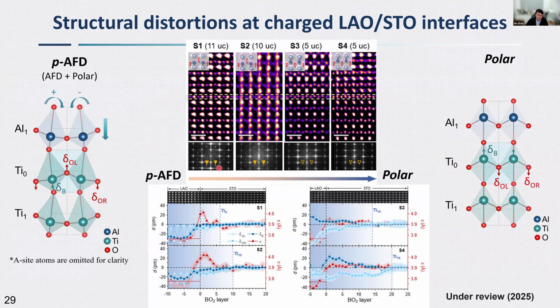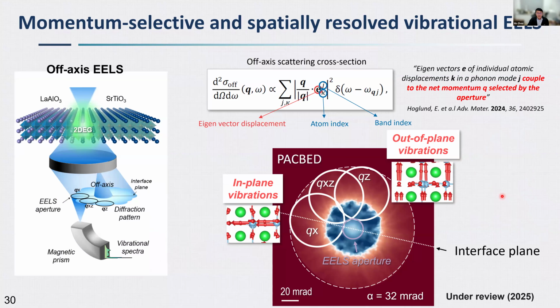But if you map out the lattice parameters, you can also see that with the charge doping increase, the structural distortion region also increases. And that's very consistent with the thickness increase of the 2D electron gas layer. And at the optimal doping, you see the structure develop into a polar structure with the structural model we show here. So we see that the electronic structure correlates with the symmetry breaking at the interface.